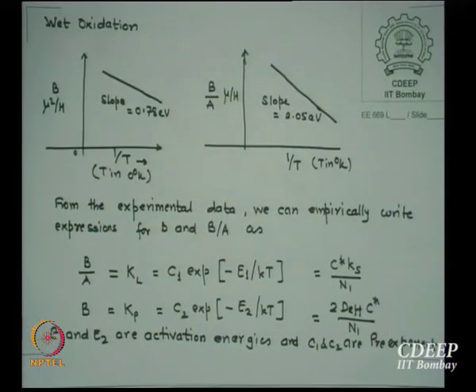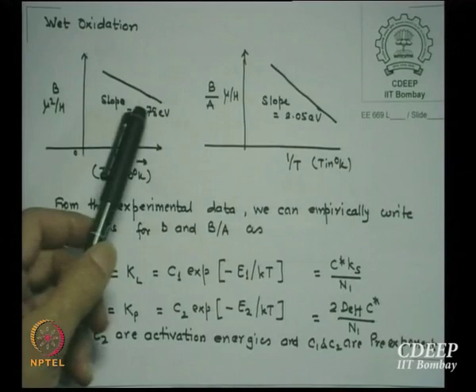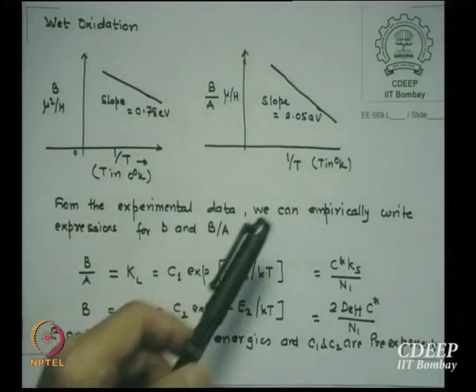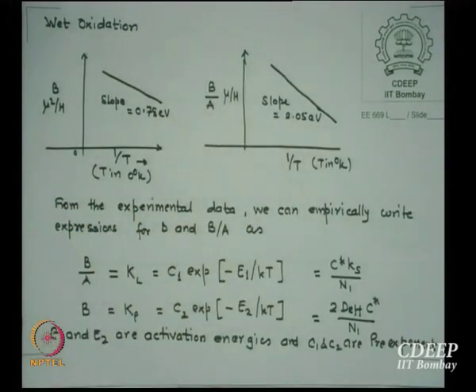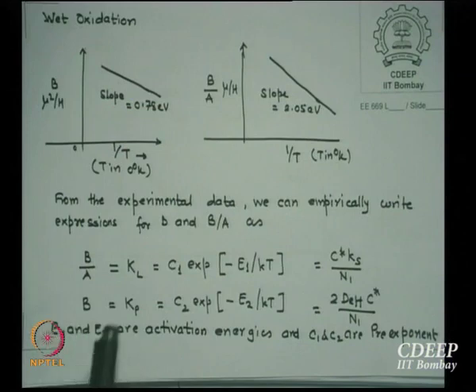So B and B by A for dry. We do wet oxidations in 95 degree water vapors. We did the same experiment for wet oxides and I find for B the slope is 0.78 eV and B by A has a slope of 2.05 eV. Let us look at this term again, B and B by A.